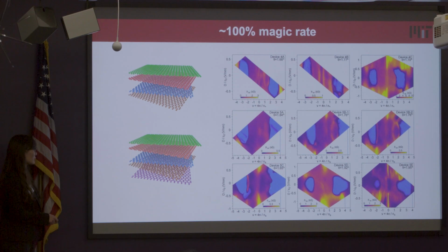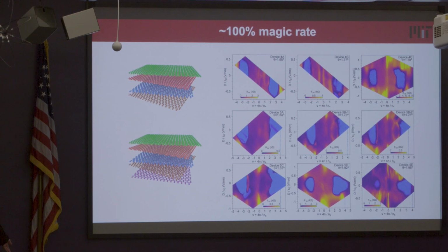Another thing I want to comment on, related to the question about the superconducting TC: I also wonder if the fact that we don't see any increased TC in the larger layer structures, where people were expecting a little bit higher TC, might be related to the issue you just mentioned. We're not really gating all of the layers simultaneously. For example, in the twisted 5-layer structure, when the theorists calculated the wave function, the flat band wave function is concentrated in the very middle layer. And we basically can't gate that middle layer because of screening. So I am curious if that leads to that.